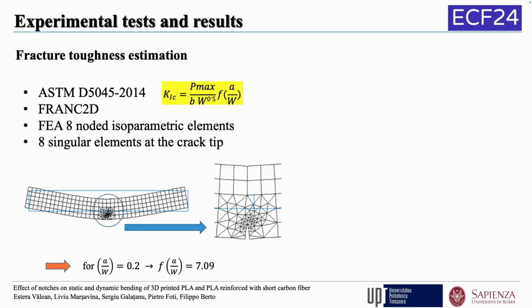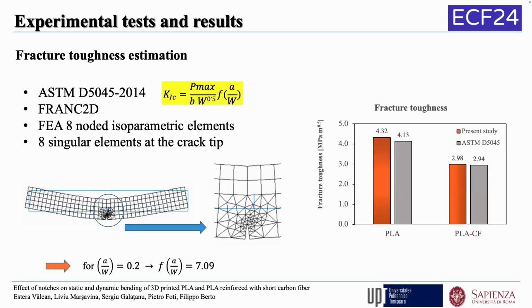So we try to estimate the fracture toughness on this static test. What I did was a calibration of this specimen, because this is not according to the ASTM standard for fracture toughness of polymeric material. So we did a very simple finite element analysis. And for this ratio between crack length and width of the specimens, which was 0.2 for these specimens, we get this non-dimensional geometry factor of 7.09. And I compared with our other results, which are related to the fracture toughness determined according to the ASTM standard. So we get quite similar results. For the PLA reinforced with carbon fiber, almost the same results, and for the other, a little bit higher values, but not so much.